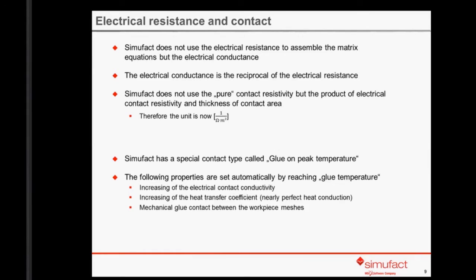A special feature I want to explain is the glue on peak temperature contact. This contact type is activated as soon as the defined glue temperature is reached, which is often the lower melting temperature of both contact partners. If the glue temperature is reached, you set the electrical contact conductivity to a very high level, the thermal heat transfer coefficient is set very high, and the mechanical glue contact is set in this area. These three properties that are changed represent the behavior of the joint.